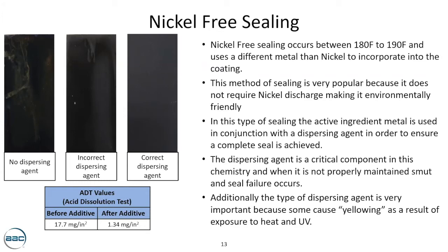The final thing to look at when you're looking at nickel-free sealing is, when you assess whether a part is good, you need to look at it from the perspective of yellowing. Many nickel-free sealing applications involve clear or electrolytic that is used for architectural applications. And when exposed to UV light or extreme heat, certain surfactants or dispersing agents will yellow. Obviously, if this is going to be on the side of a building or a storefront, that is not an option. So it's absolutely critical to understand the type of surfactant you're using and the risk of potentially yellowing that could occur, because for the nature and the application of these non-nickel seal products, that cannot happen.